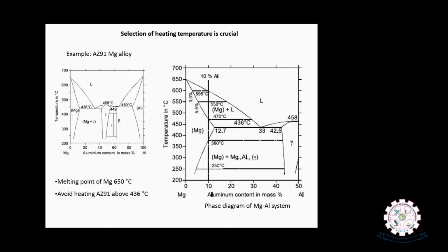So if you consider, for example, magnesium and aluminum alloy, AZ91 magnesium alloy, this is the phase diagram of the magnesium-aluminum system. You can notice at 436 degrees centigrade, you will be getting liquid state, liquid phase. Therefore, if you want to deform the magnesium alloys, which have magnesium and a considerable amount of aluminum as alloying element, the processing temperature must be less than 436. In fact, we should not go close to 436, as we know, right? And in order to initiate the prismatic planes and pyramidal planes to slip, at least we should heat above 250 degrees centigrade. Therefore, there is a range. So there is a band between the minimum and the maximum allowable temperatures, where we can heat the magnesium alloys and deform them comfortably.